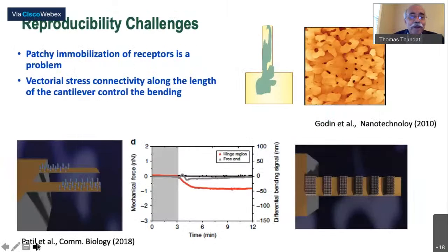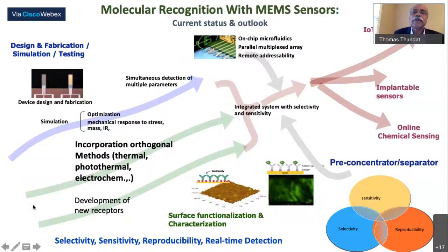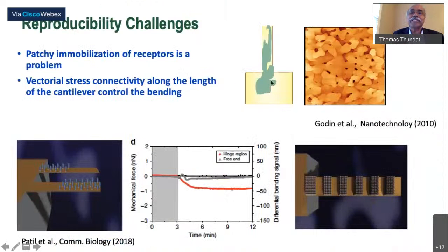And so another problem I talked about was reproducibility issues. We make a cantilever, say 100 cantilevers, with a self-assembled monolayer, uniformly put on the surface in lab conditions. But when you look at the response, there is a big distribution in the response for the same analyte, same concentration, for 100 identically prepared cantilever devices. The reason is that if you look at the gold, for example, deposited on the surface, it has grains and things like that. On top of that, it's patchy. That means it is not uniform.